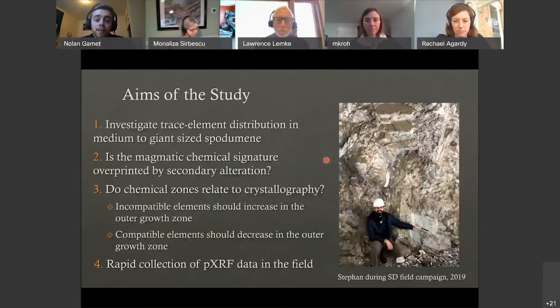The biggest aims of this study were to first determine why and how these giant crystals form. To do this, we investigated trace element distribution in the medium to giant sized spodumene, and asked whether the primary chemical signature is overprinted by secondary alteration. And then, do these chemical zones relate to crystallography? If this is the case, the incompatible elements should increase in the outer growth zone, and the compatible elements should decrease in the outer growth zone.